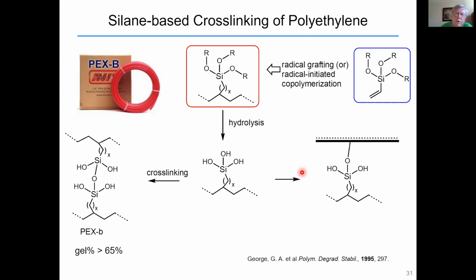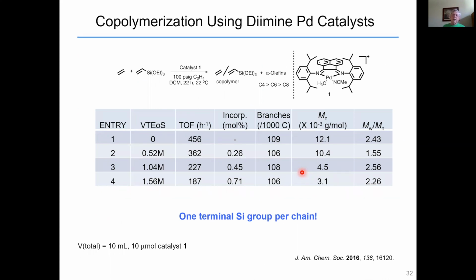So we decided to take a further look at this, and I'll show you some mechanistic work that turned out rather nicely. We collaborate with DuPont on a lot of this chemistry, and they did some early work in this area, and we followed it up with a lot of further mechanistic studies. If you copolymerize ethylene and this triethoxyvinyl silane with this palladium methyl nitrile complex, you make the copolymer. This is 100 psi ethylene at room temperature. You make the copolymer, but if you look closely, you also see butenes, one butene, one hexene, and one octene, and maybe a trace of the C10.